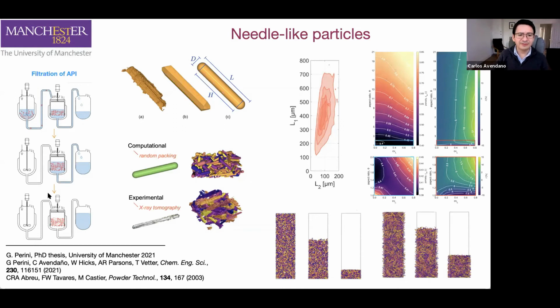However, this filter cake formed here has a certain degree of porosity. And most likely a lot of the solvent is trapped. Typically these are very harsh solvents that you need to completely remove if you want to put these kinds of particles in tablets for human consumption. The problem is that we need to remove that trapped solvent. Therefore, we need to do a series of washes to do that. That's one of the most expensive steps in the pharma industry. And it's expensive because typically these filter cakes have very high density.